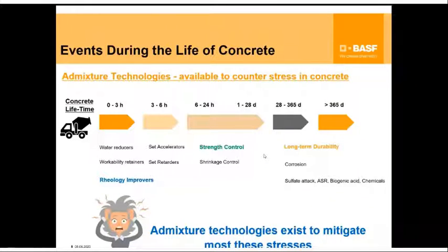The 6 to 24 hours is actually a very critical phase for concrete. It's almost like a child. This is the time period where you got to take very good care of your concrete if you want really strong concrete later. This is where all of your initial strength control comes in. Shrinkage related activity starts to happen, which has to be taken care of. And then as you go from 6 hours to 28 days, if you can take care of the concrete during this period, it will reap a lot of good benefits for the rest of its life that you give, whatever it is, 100 years, 50 years, right?